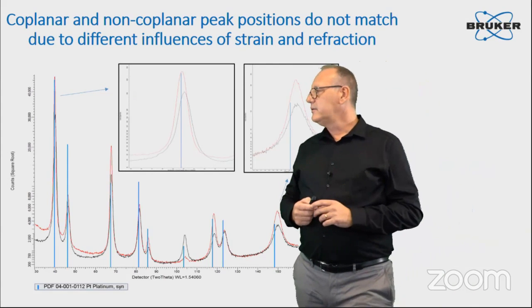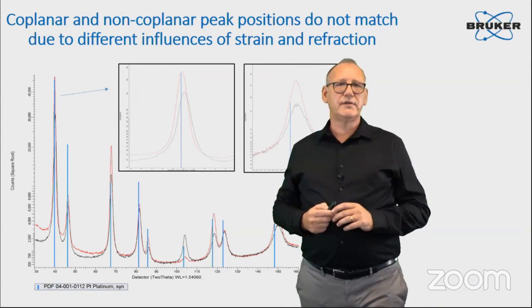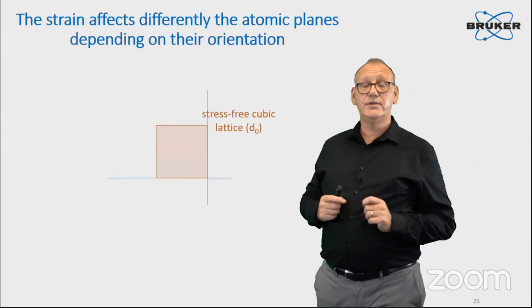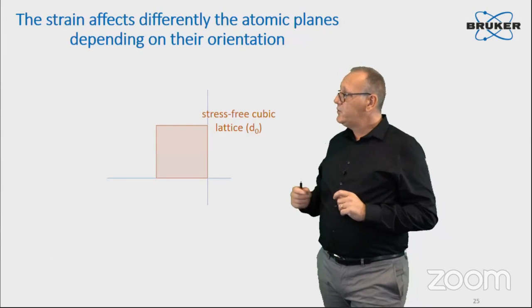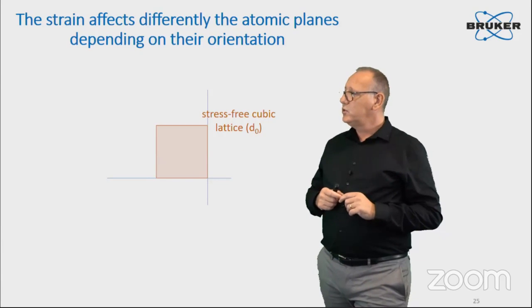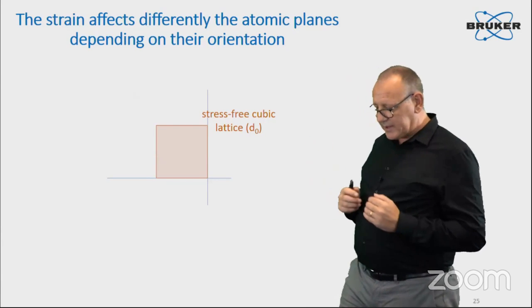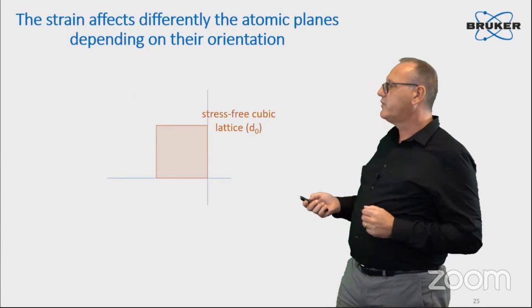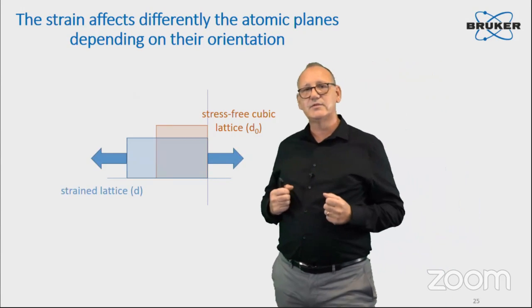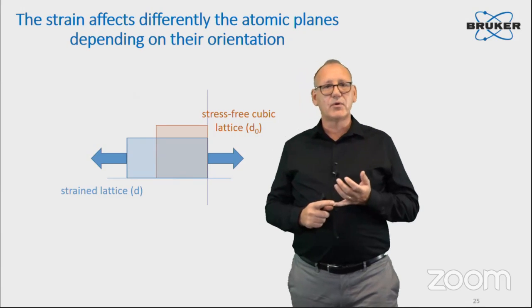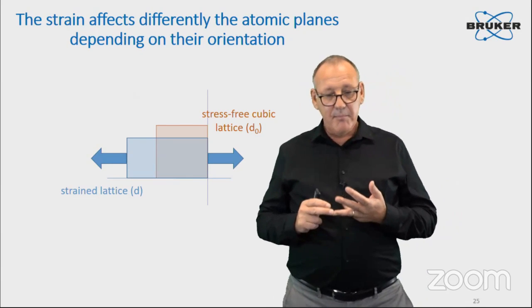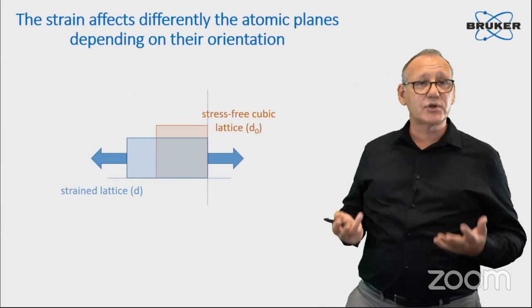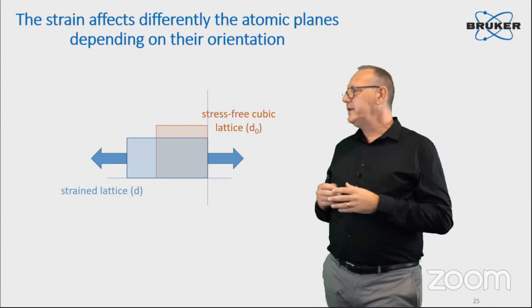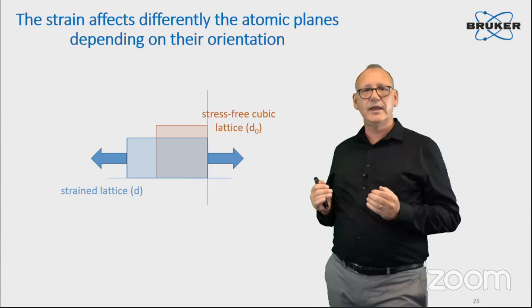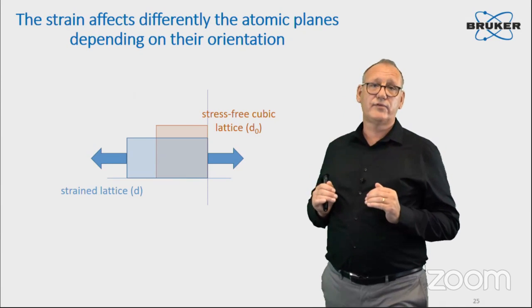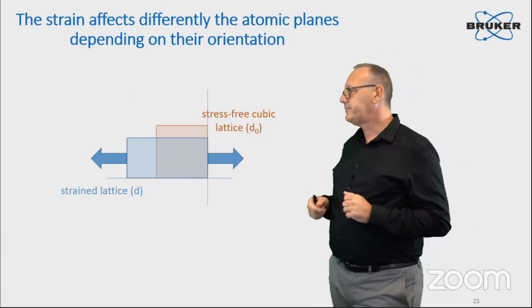One of the key reasons for this shift is actually the residual stress in your thin film. If you consider a stress-free cubic lattice, and you deposit this material with a very small thickness, it's most probable that the lattice will be strained. It depends on the growth condition, it depends on the method of growth, it depends on the temperature of growth, it depends on many things. But my experience is that the thinner the layer, the more chance you have to find strained lattices.